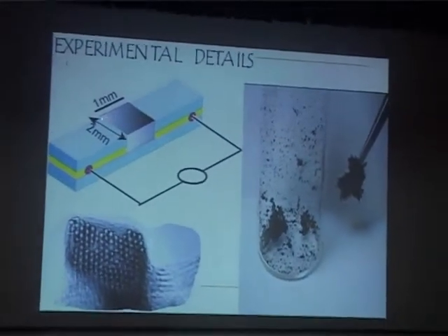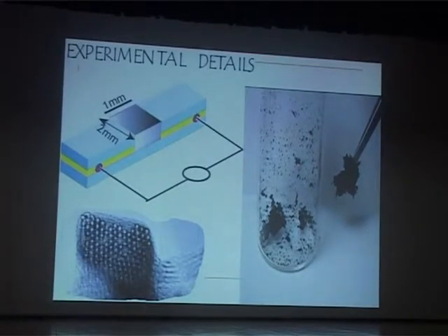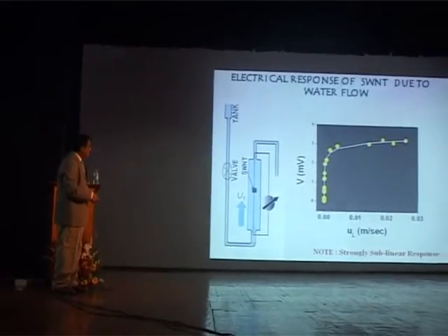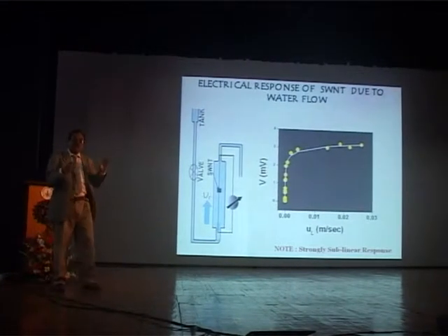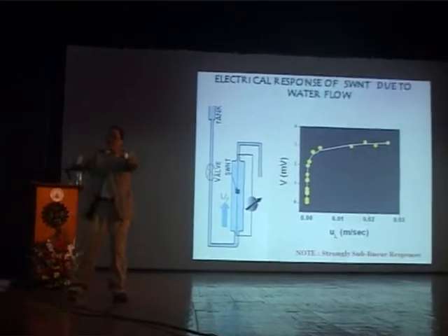And this was done in a very simple minded fashion. You make flow alignment of the tubes between them, put these two gold electrodes and flow liquid over it like this, and what you generate is the voltage. Now this voltage is the flow induced voltage, only coming when you have a flow. And this you can see it is in millivolts, and this is the average velocity of the liquid. It is highly sublinear. So our idea was it would be linear, because the flow will drag the electrons. So current will be proportional to the momentum transfer, and we will get a linear relationship,